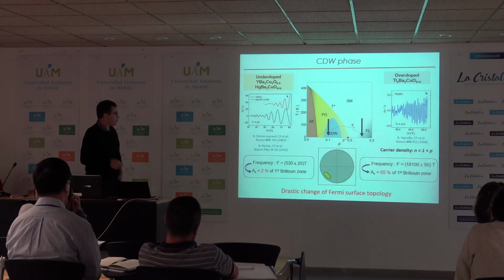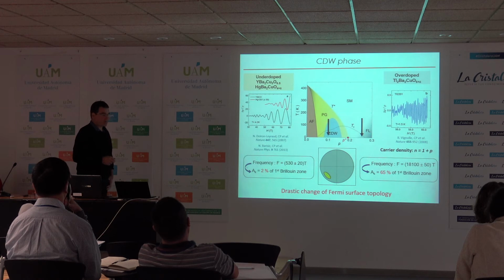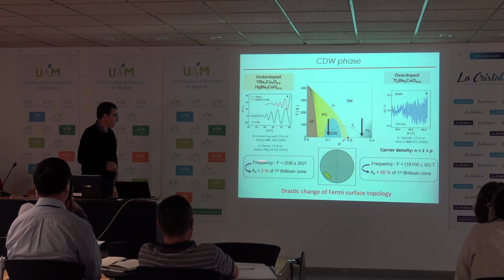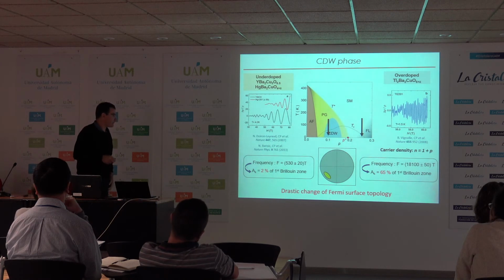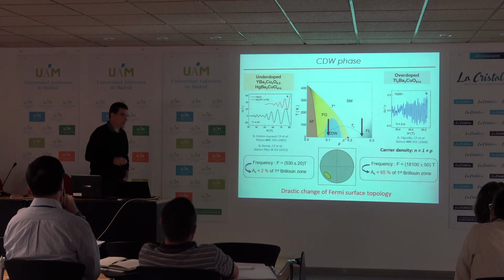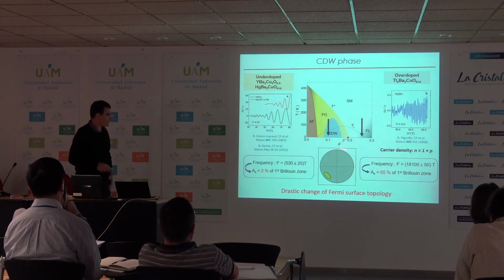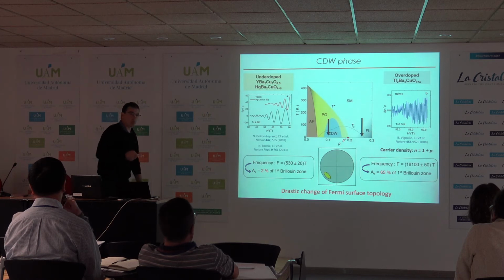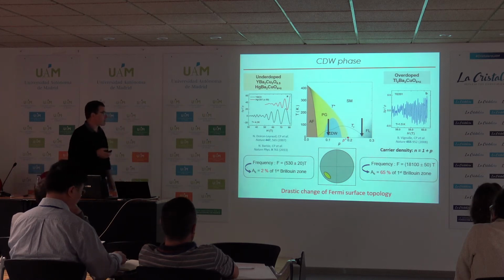In both compounds, the frequency of the oscillation is very small compared to what we have found in the other thallium 2201. Namely, for YBCO, the frequency is around 500 tesla, which only corresponds to 2% of the first Brillouin zone, compared to 65% for thallium 2201. So this measurement shows you that there is a drastic change of the Fermi surface topology on both sides of the phase diagram.